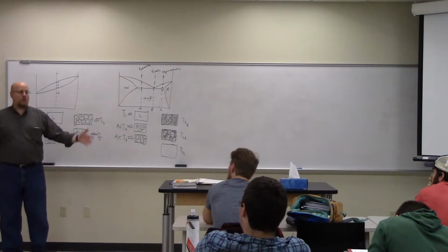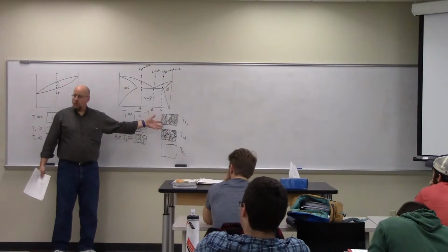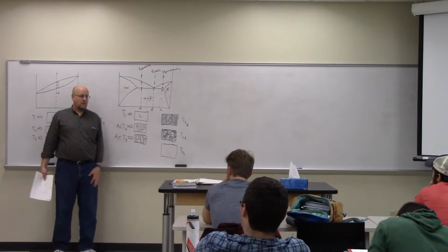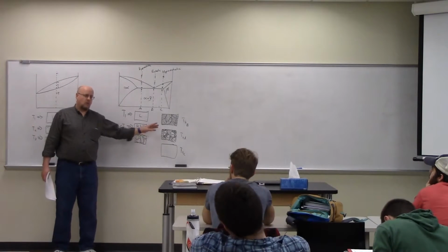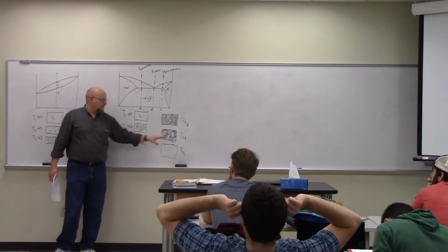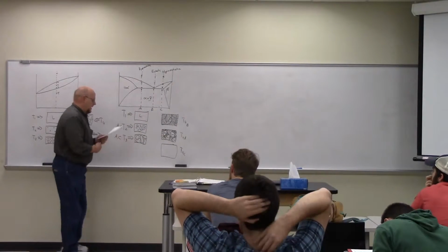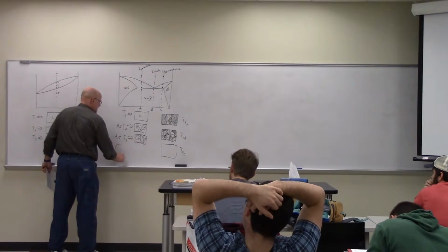And again, if you cool slowly, then the lamella are thick. If you cool quickly, the lamella are finer. But they're all lamellar. And again, it can be nodular, but I'm just drawing it all as lamella so you can see it. You know what I mean by nodular?